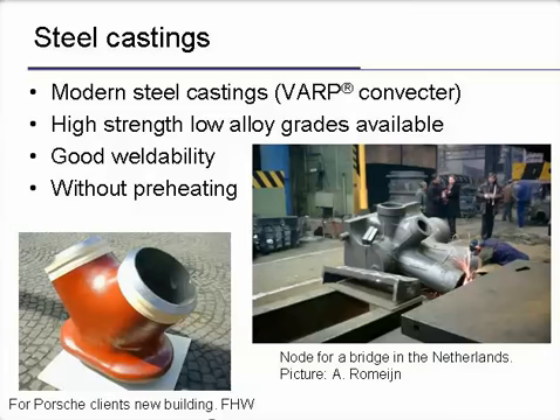Now, furthermore, today you have modern steel casting methods. I will show some types of steel you can obtain using what is called the VAR converter, which stands for vacuum argon refinement process. That's what is done by Friedrich Wilhelm Hütte in Germany. With this, you can get very high strength, low alloy grades, all kinds of different grades, and you also get very good weldability. And depending on the type, you can weld without preheating.